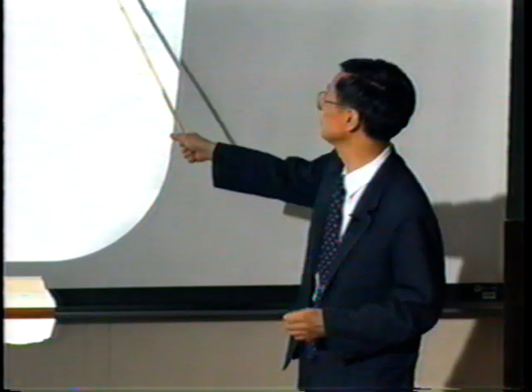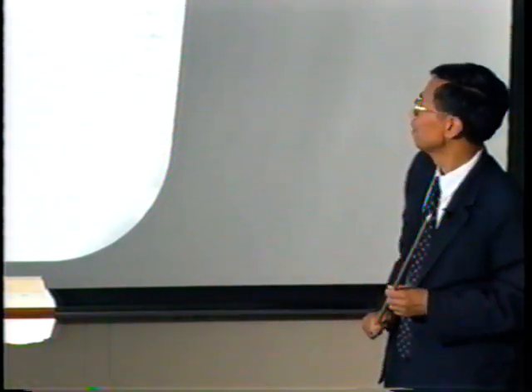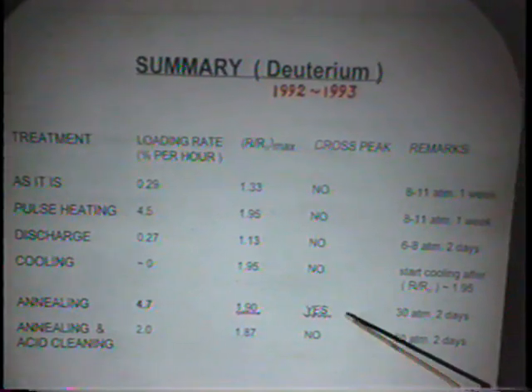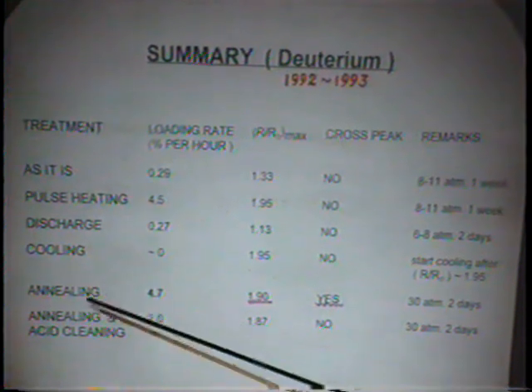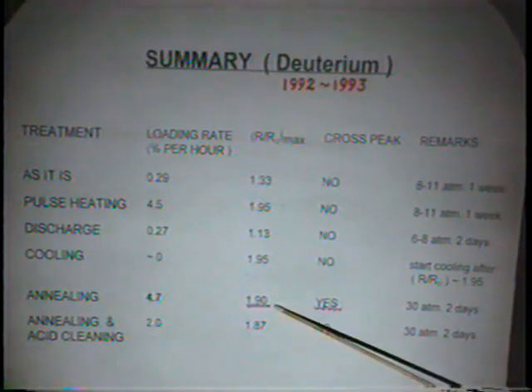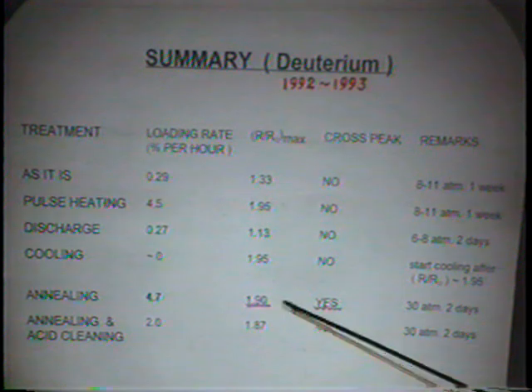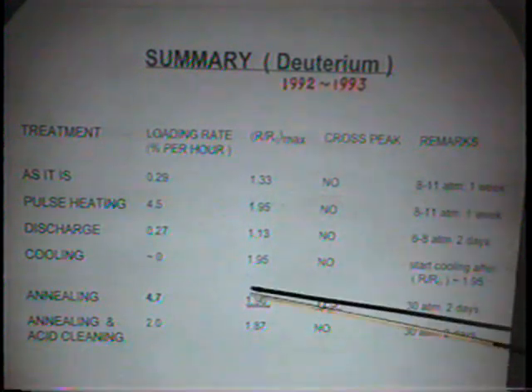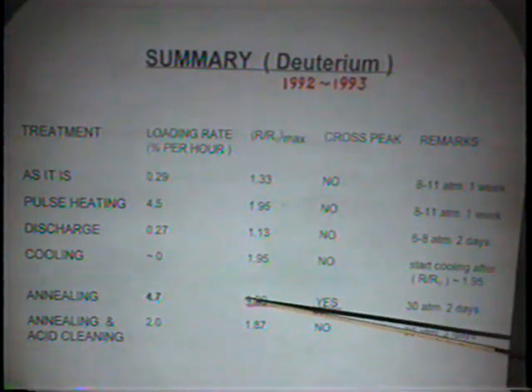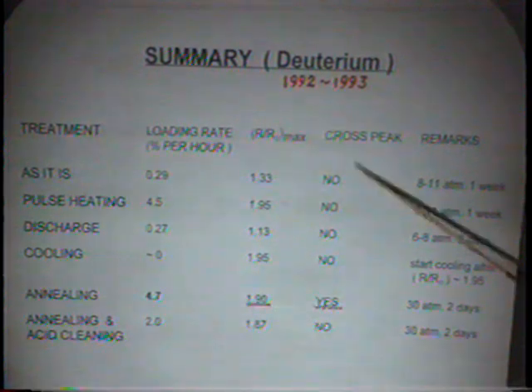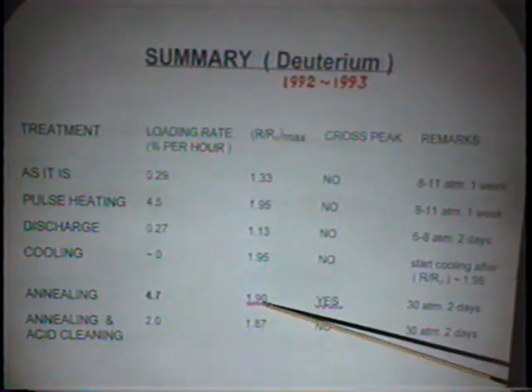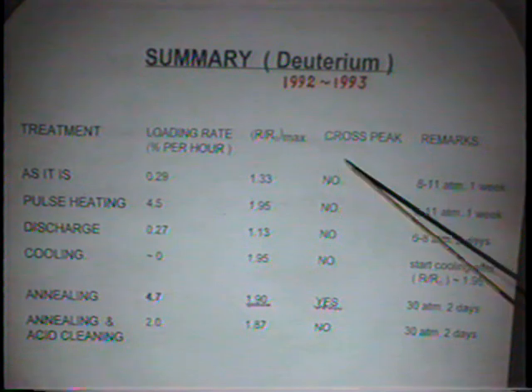That's in 92 to 93. Only one using the annealing, we crossed the peak and reached 1.9. So the peak is 2 for the deuterium loading curve. The peak, the resistance should be 2, so crossing the peak, going down again, 1.9.